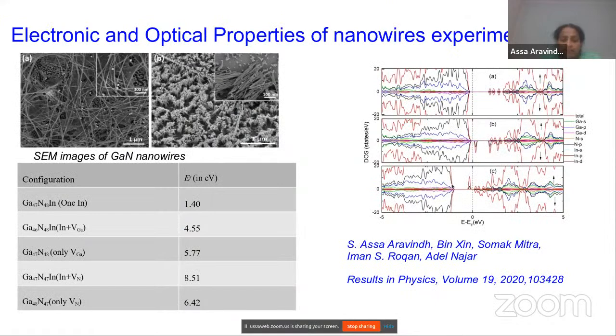Now, there is also a lot of, actually we use this very routinely, but I'm just giving you a flavor of how we can compare with different materials. So this is gallium nitride nanowires, again with doping, and in this study, the experimentalist has seen that there is a significant change in properties occurring because of the presence of defects. But it is very difficult to confirm the presence of defects directly. But DFT can help there.